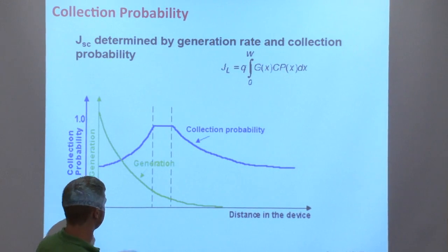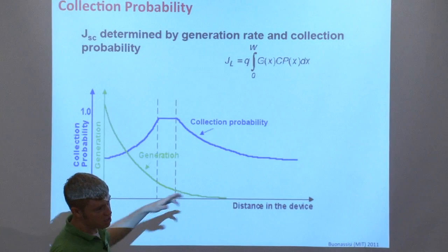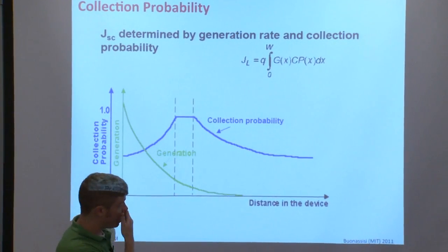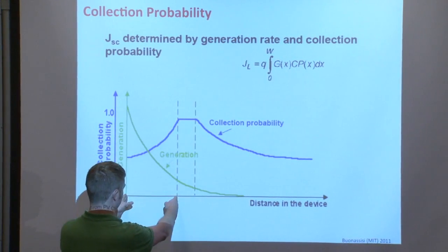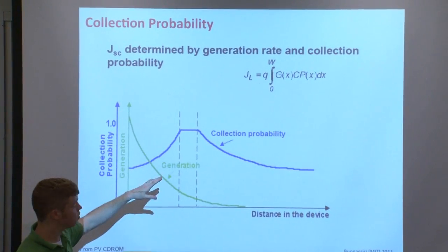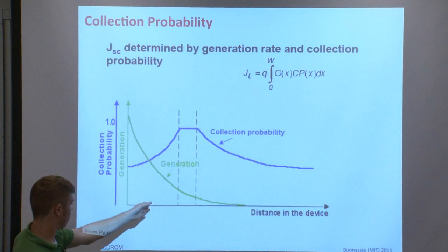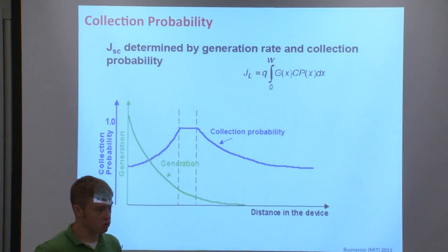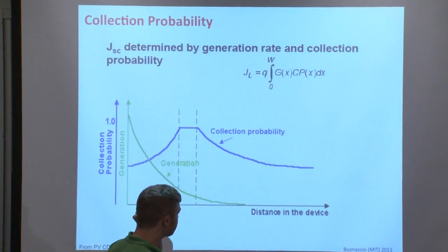For most models, you assume that, first of all, the space charge region is very, very narrow. It's almost assumed to be negligibly thin. The emitter is generally very short, and the diffusion lengths are so poor in the emitter, for reasons we'll get to soon, that it's almost a dead layer. Your response at the very short wavelengths, where you're absorbing most of your light in the emitter, generally doesn't add to your short circuit current. We'll talk about that soon. Excellent question.